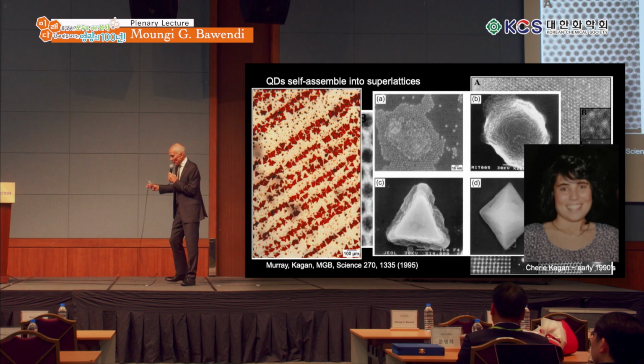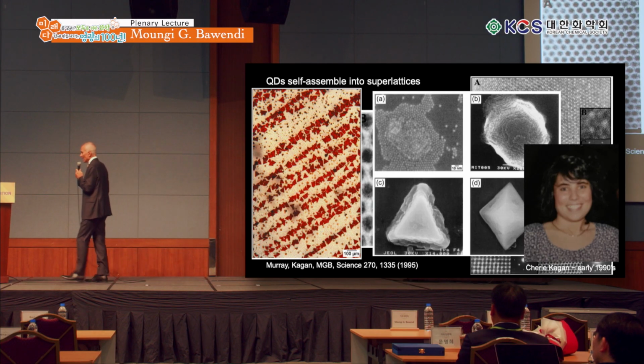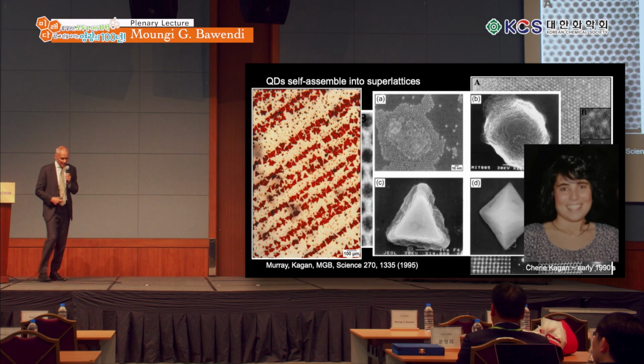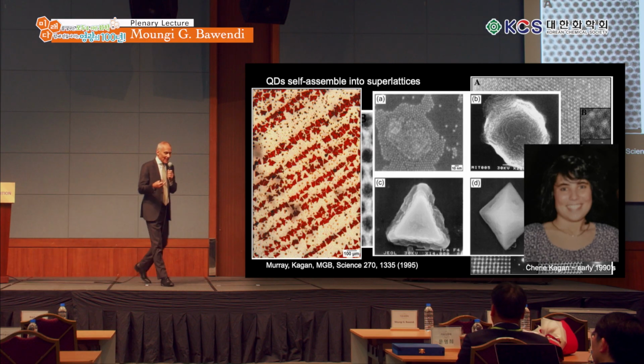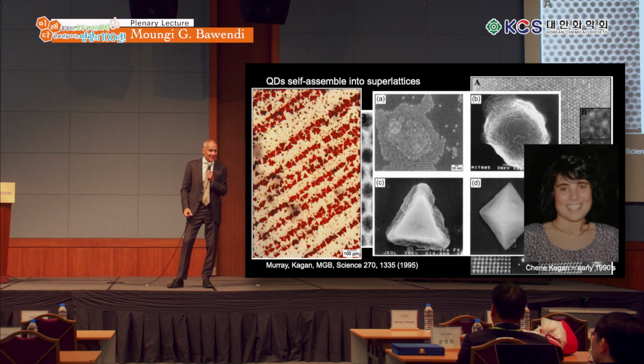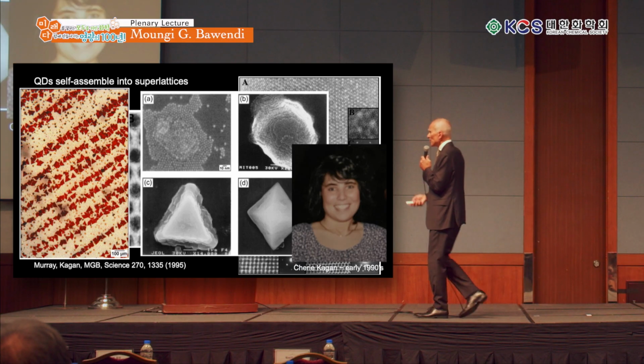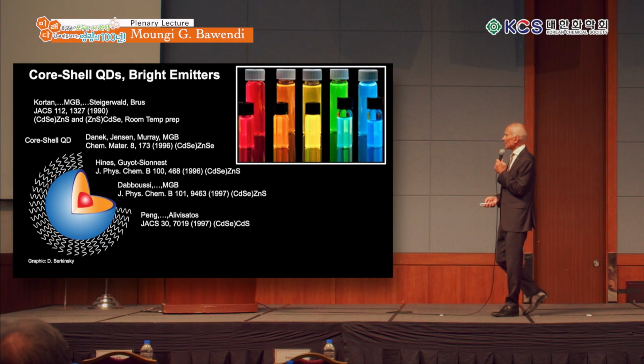Another thing that you see when you make very good samples is that when you dry them, the particles arrange themselves in a lattice, like an artificial solid. And this was the beginning of thinking these are artificial atoms, and we can make artificial solids, and maybe they'll have interesting properties. Using small particles as a new periodic table and trying to create new solids with new properties. And they could be pretty large, and this is Cherie Kagan that worked on this.